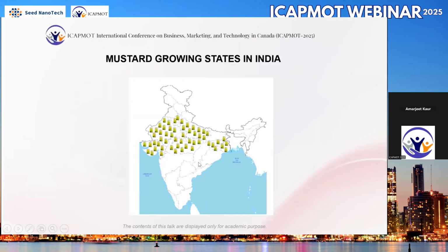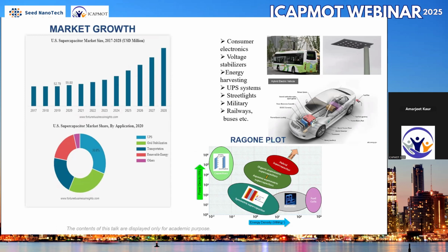Any supercapacitor is characterized by two things, the power density and the energy density. Power density is a measure of how quickly this energy can be delivered. The rate of change of this electrostatic energy gives you the power density. Generally we have the case of a symmetric supercapacitor, where both the cathode and anode, the positive and negative electrodes, are symmetric. There the energy density is low, and the energy density for batteries is comparatively higher, while the power density for a capacitor is very high. In a conventional capacitor it is of the order of 10 to the power 5. In the case of a supercapacitor, the power density lies between 10 to the power 4 and 10 to the power 5 for research grade devices.